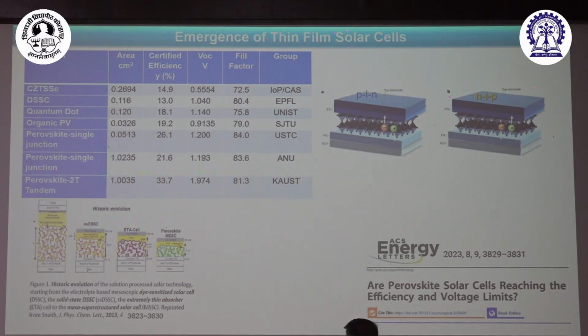And this is what you get from what we call thin film solar cells. Professor Patil mentioned thin film solar cells. There is an NREL chart. They put out these numbers. Okay, so we analyze those numbers based on area, certified efficiencies, VOCs, fill factor, and which group did it. The way we started in the 90s was the dye-sensitized solar cell. Until then, only PVs and maybe CIGS type materials were used. This was a liquid junction cell. Then we started solid-state dye-sensitized solar cells. Instead of a redox couple, people use hole conductors. Then we went to the quantum dot solar cell or extremely thin absorber cell, where you can use the SILAR method and make these thin film solar cells.